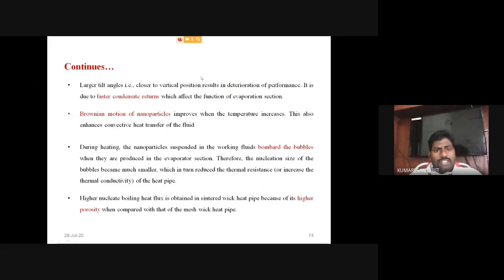Then at a larger tilt angle, okay, even if you are tilting the sintered wick heat pipe beyond 45 degree inclination, closer to the vertical position, it results in deterioration of performance. It is due to the faster condensate return, which affects the function of the evaporator section. The next, the Brownian motion of the nanoparticles improves when the temperature increases. So this is also favorable for the convective heat transfer property of the working fluid.